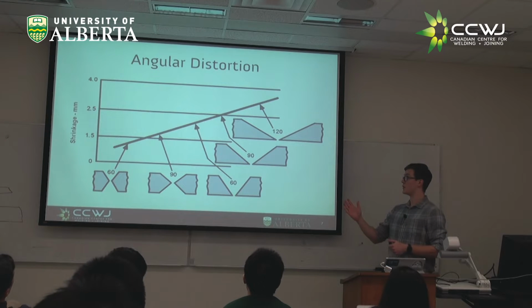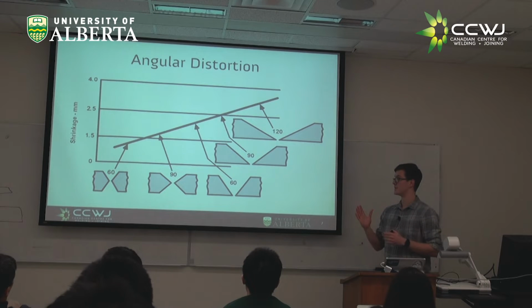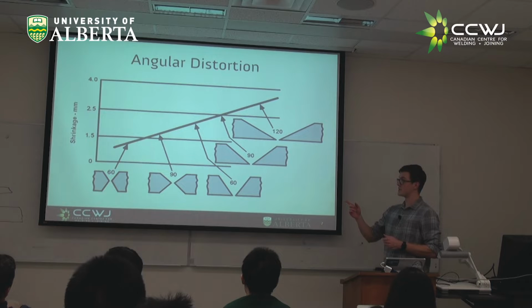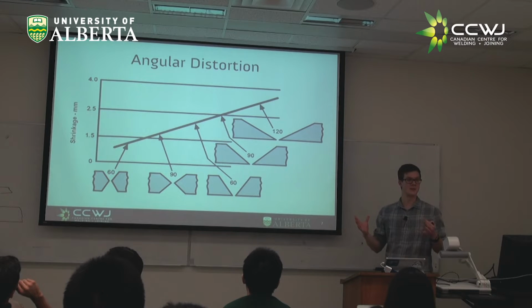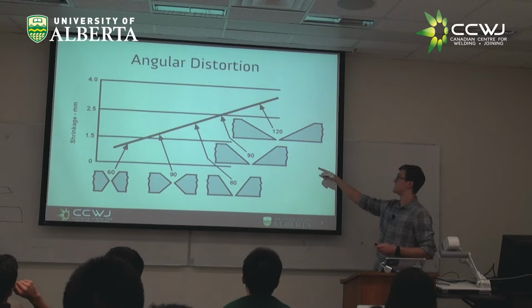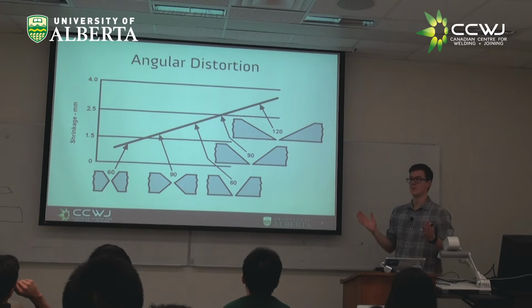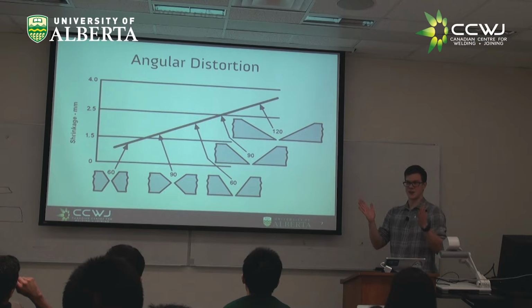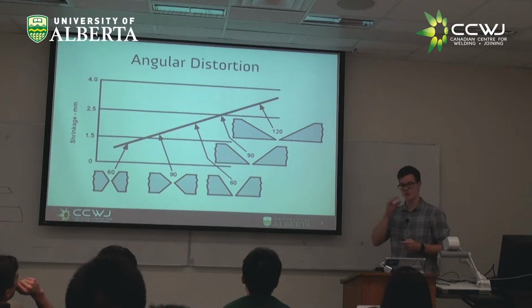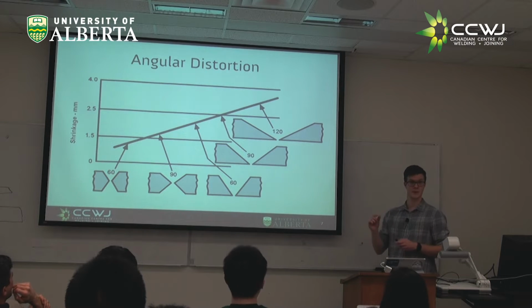Similar idea, but now looking at a whole bunch of different bevels. You can see that it's not just the angle of the bevel in the double-sided versus single-sided, but as you compare these different geometries, more metal is also going to make a difference. So if you look at 60, 90, and 120, all three of those are the same one-sided weld. But as you get more volume of weld, what we learned, I think, 3 classes ago when we did the calculation, if you look at the deposition, you can draw a relationship between deposition and heat input, which is roughly about 60 joules per millimeter of length per millimeter squared of weld deposit, or 60 joules per millimeter cubed.